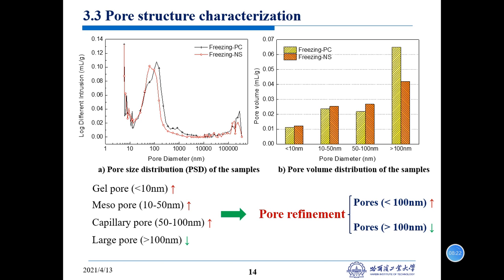The figure is a pore size distribution, and in order to get a more detailed understanding of the PSD, we divide the pores into 4 ranges: gel pores, mesopores, capillary pores, and large pores. Like this figure, you can see it clearly. We can see the addition of nanosilica increased the volume of gel pores, mesopores, and capillary pores, and also decreased the large pores. In other words, the nanosilica achieved pore refinement like this.